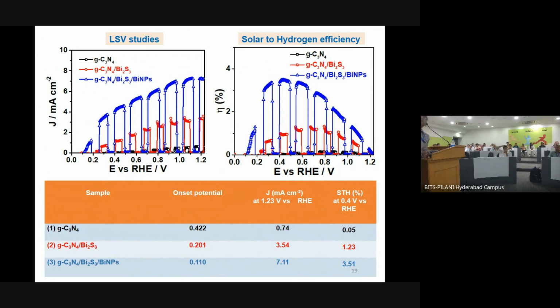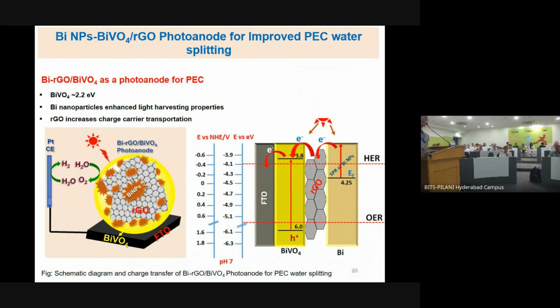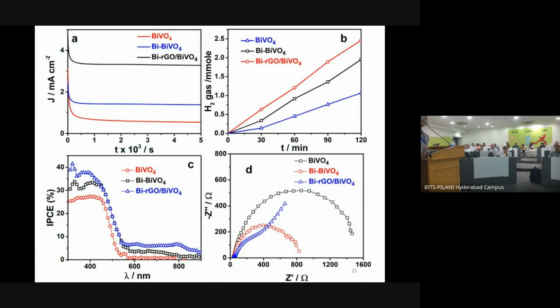The known combination you can look at. The same thing you can also play with other combinations. Instead of bismuth nanoparticle, you try to do the same thing on, for example, RGO instead of C3N4. You can also see some kind of an effect. But once again, all these things boil down to one good part, that they're stable. They give continuous hydrogen evolution, and you also look at those IPCE values.